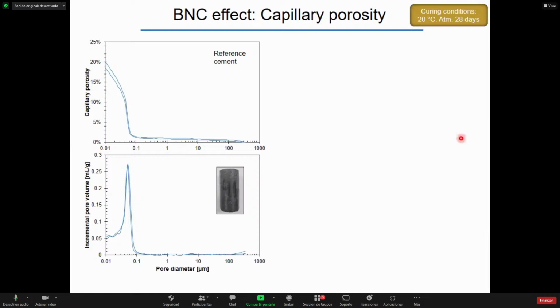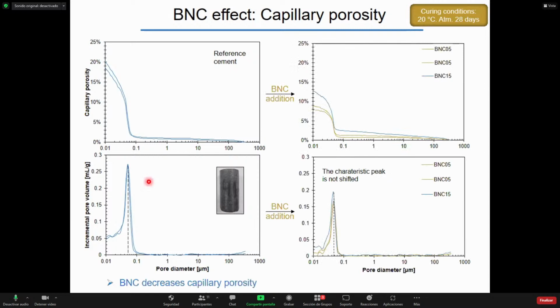Initially, the reference cement had a capillary porosity of 20% with a characteristic peak of 50 nanometers, or 0.05 micrometers. But when we added bacterial nanocellulose, we saw that this value decreased below 15%, but the characteristic peak in this case was not shifted.